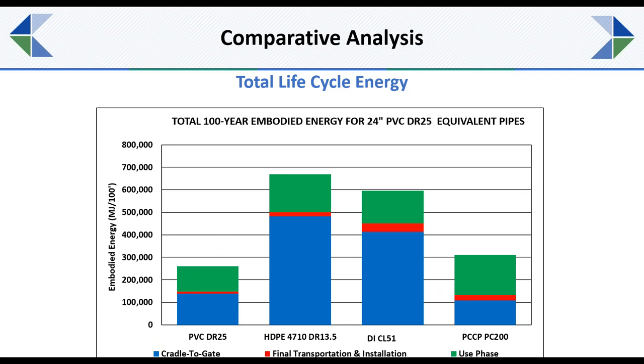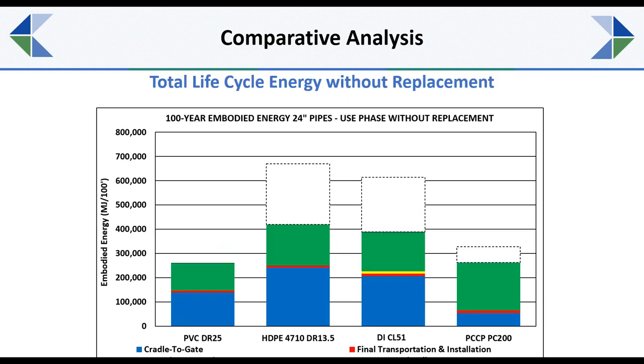And then for the 24-inch, similarly, you see PVC pipe does have a lower requirement, roughly 61% less than HDPE, 56% less for ductile iron, and roughly 17% less for PCCP. Now, just to be fair, we did look at those initial numbers included the energy required for replacement of the pipe, because again, we do look at the 100-year life.